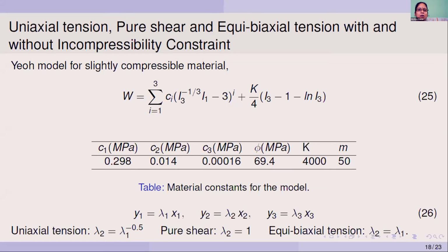So this W is the strain energy density for the intact material behavior. So here this I3 is the third strain invariant, and this capital K is the bulk modulus. And this value of the bulk modulus is obtained such that the stress strain response for this slightly compressible material and the stress strain response for the incompressible material coincide.